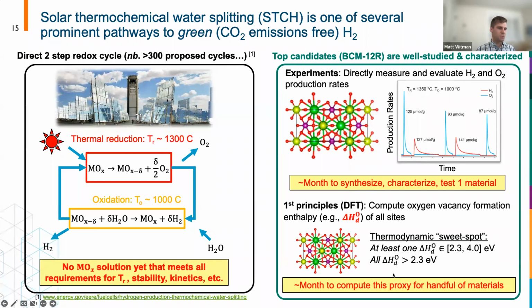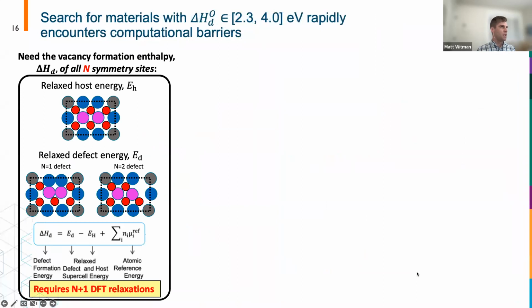So you can do this for a handful of materials, but it still takes a long time if you're going to do this with DFT. And the reason is because we need to have a host structure that we relax with DFT, and then we have to compute that vacancy formation enthalpy for all the symmetry sites in the crystal. So if there's n symmetry sites, we have n+1 DFT relaxations we need to perform, but we can do that and compute this delta H of vacancy formation enthalpy.